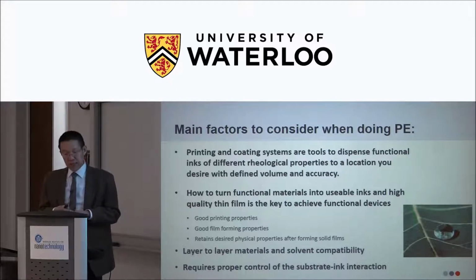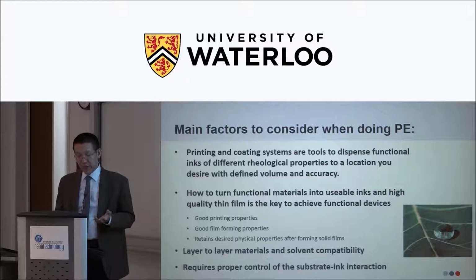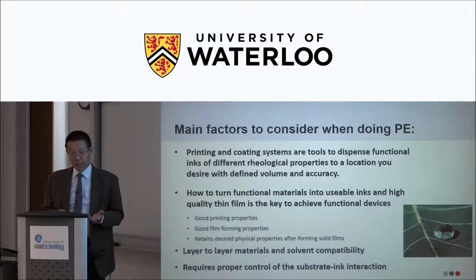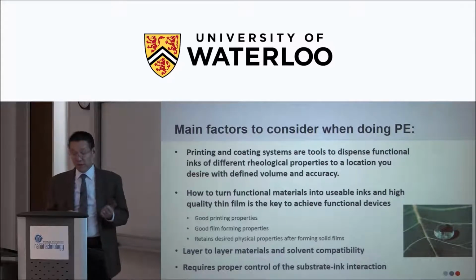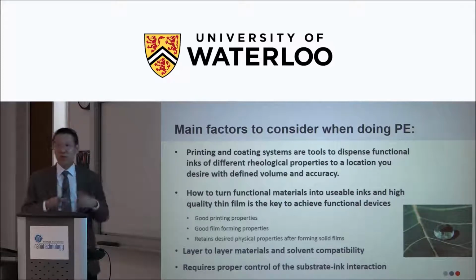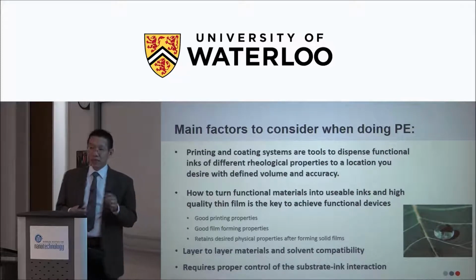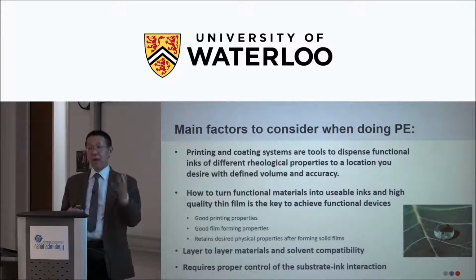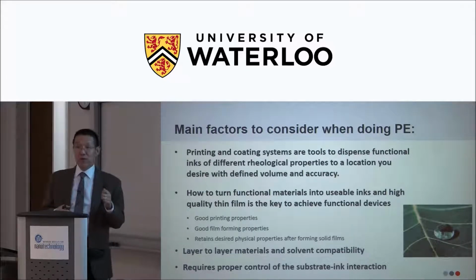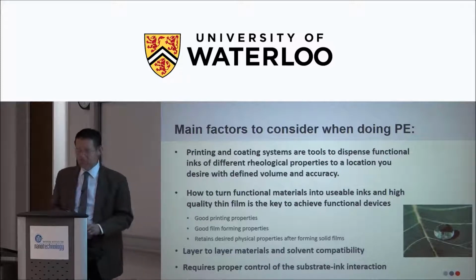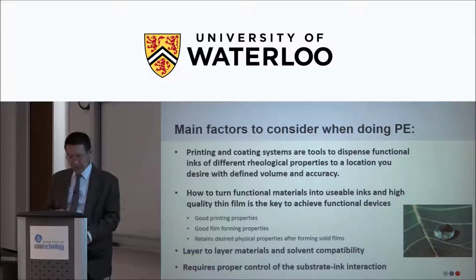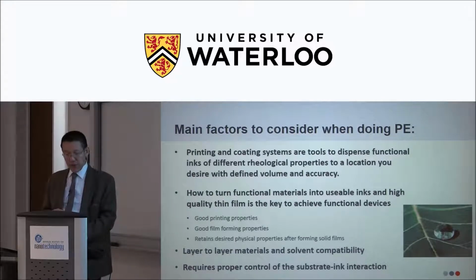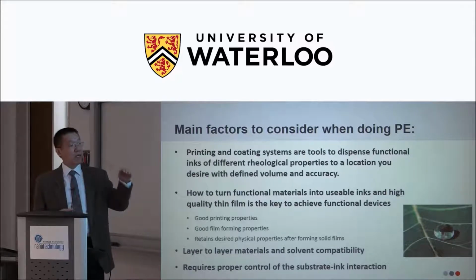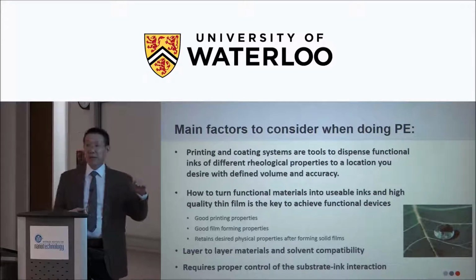So when you make functional inks, you have to have good printing properties, and then you have to have good film forming properties. And after drying, they need to retain the physical properties you want in either the polymer or nanoparticles you designed at the beginning. So it's not always the case. And also, how to solve layer-to-layer solvent compatibility issues.